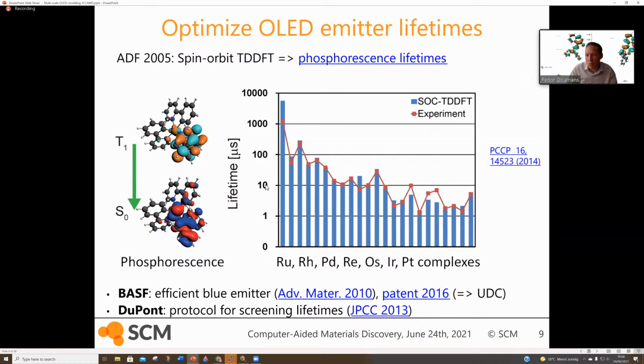And as you can see all across the range, typically you get pretty good predictions from this spin-orbit coupling TDDFT. So you can use that as a screening tool to quickly find what would be an emitter with a high lifetime, because you want a high lifetime. You want to make sure that once it's in the triplet state, it emits the photon, because otherwise you have a higher chance of getting non-radiative decay processes, which lead to worse conversion, and it also leads to potentially building up energy and breaking molecules and killing your pixels.